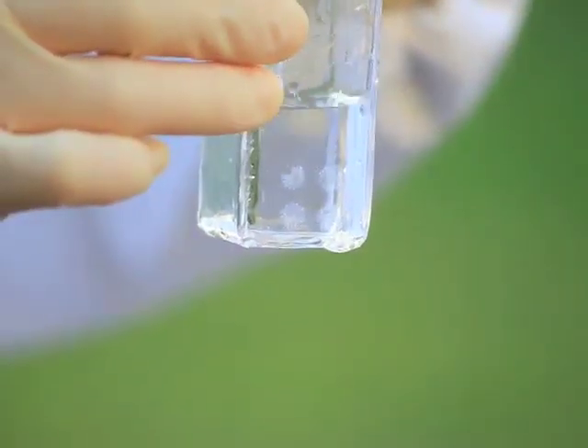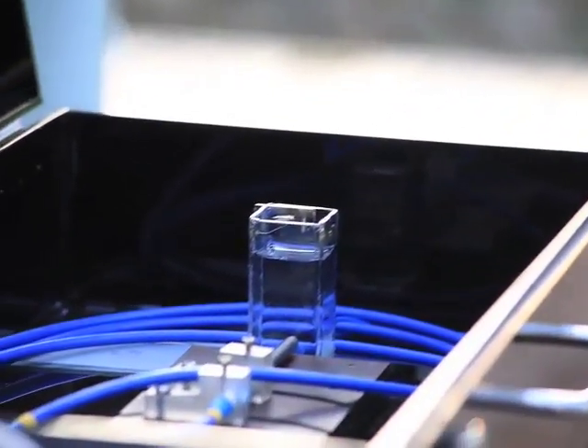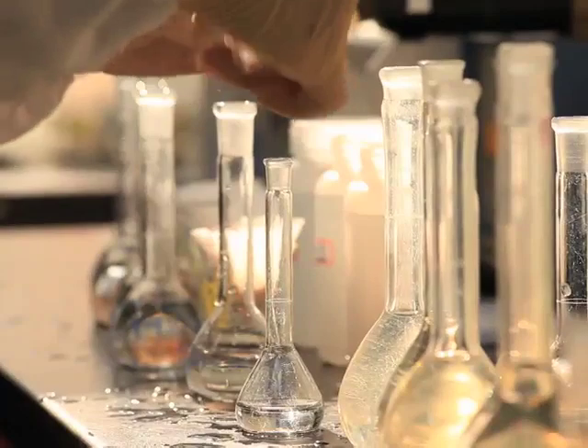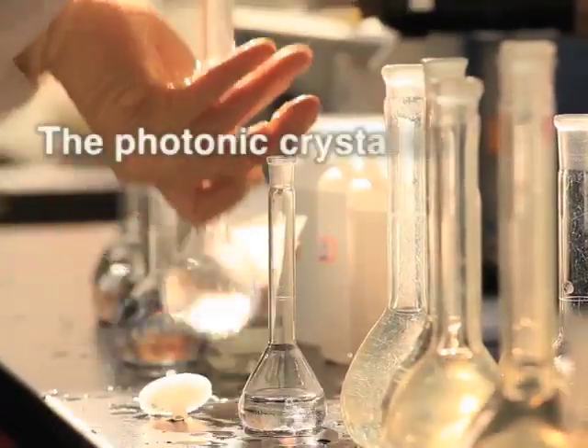The detection of BPA is conducted simply by putting the photonic crystal detector in a solution sample. Any BPA in the sample is absorbed by BPA molecular imprinted nanocavities on the photonic crystal sensor, causing changes in the sensor's refractive index which can be observed as a shift. The BPA concentrations can be determined by the Bragg shifts of the photonic crystal detector.